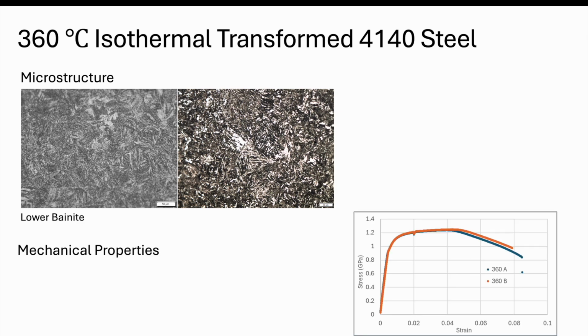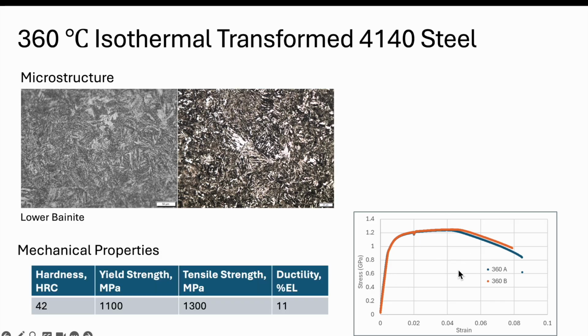Now the properties. These are the engineering stress strain curves for a couple of samples at 360. Again, you'll notice the elastic and plastic regions. When we crunch the numbers, what we see is that the hardness drops a little bit to 42 or so.